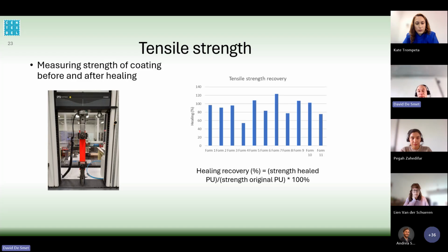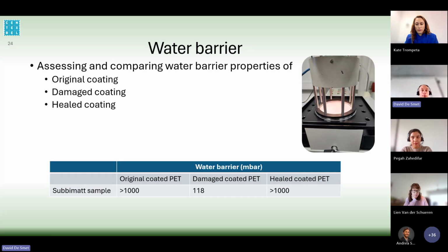And this is shown here in the table for different formulations. And it's clear here that for most of the formulations we made, we have a good healing behavior, which most of the time is above 80% and also around 100%. So here we can already see that not only visually we can see a restoring of the coating, or we can join two broken parts into one, but also the strength is recovered.